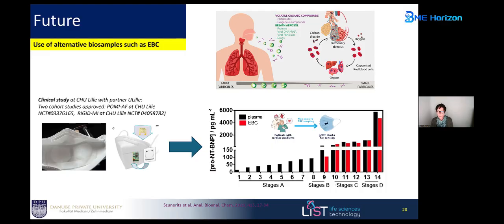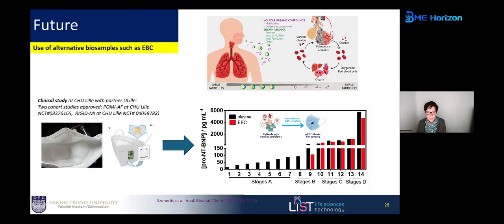definitely interesting. And this is what we could show more recently, again on cardiovascular patients. If we collect the breath in the form of a breath condensate, or masks which you can cool down, and then we dose the NT-proBNP level in these patients, we could, if you compare the plasma with the EBC level, see a certain correlation between the EBC and the plasma. And what's interesting is that stage A people, people who have almost no cardiac problem, we see nothing in the EBC, but at higher stages we get more and more NT-proBNP biomarkers in the breath. That means this could be an interesting alternative for thinking about some new biosensors.